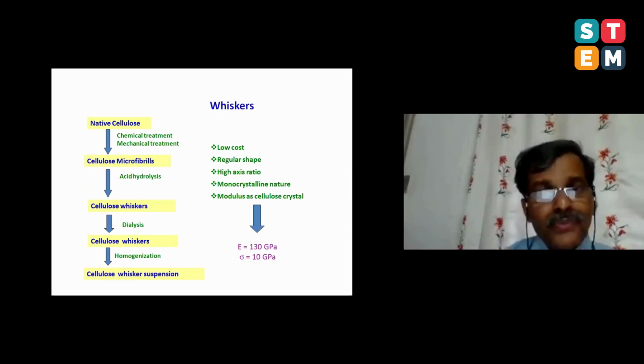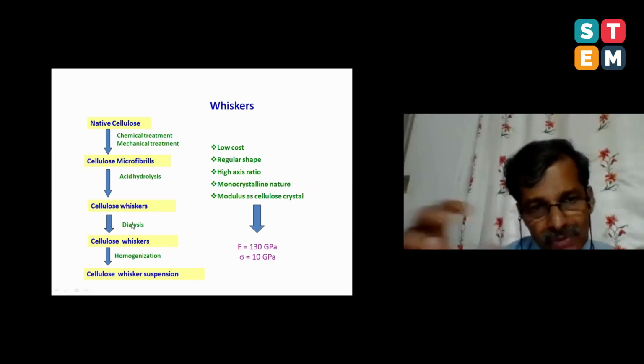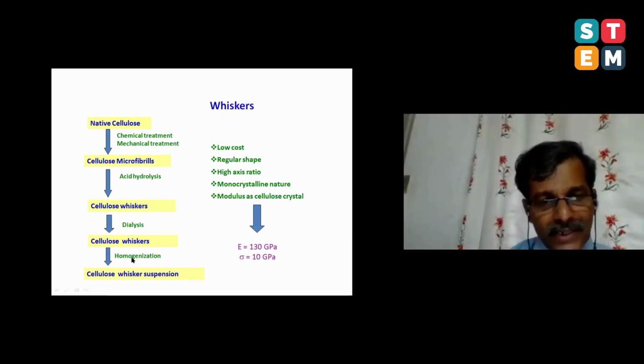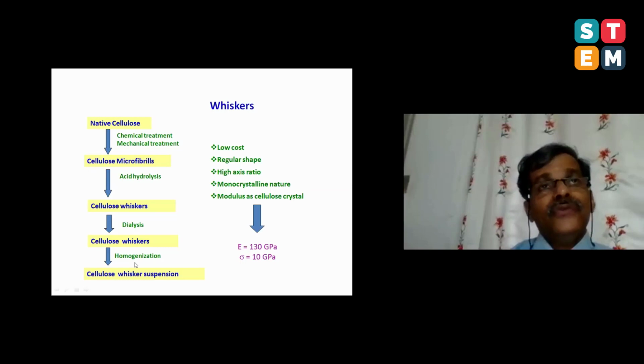Look at the summary of the process. You collect the agro waste. You go for a mechanical treatment, chemical treatment, acid hydrolysis, dialysis to remove the acid, homogenization, and finally, if you use a strong acid, you get very short nanofibers.